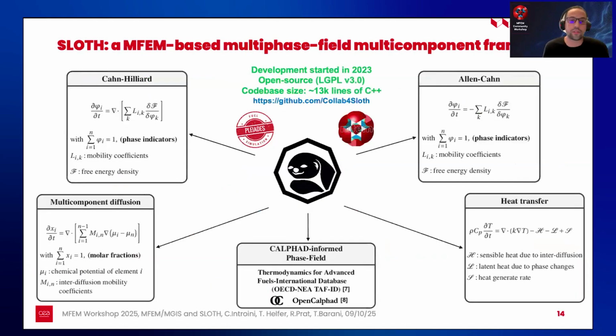So we have developed SLOTH on top of MFEM in C++. It's a small code developed since 2023. It's open source, developed under LGPL license. SLOTH provides the Cahn-Hilliard equation, the Allen-Cahn equation, but also the multi-component diffusion equation and heat transfer equation. And in order to perform the multiphysics simulations of interest for our nuclear applications, we have also a coupling between computational thermodynamics and SLOTH in order to perform CALPHAD-informed phase field simulation.